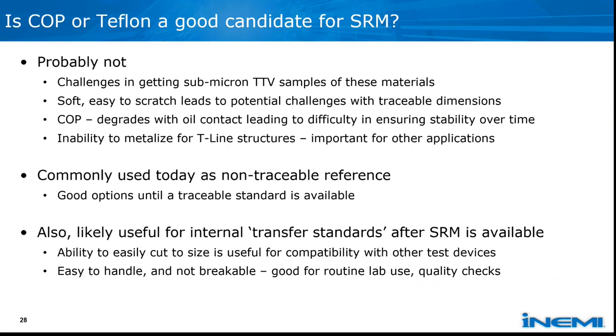So is COP or Teflon a good candidate for a standard reference material? Probably not. The challenges in getting sub-micron thickness variations of these samples is very high. They're soft and relatively easy to scratch, which has potential challenges with traceable dimensions. COP is known to degrade with oil contact, leading to difficulties ensuring stability over time. And neither of these can be metallized for use with transmission line structures that are important for other applications.